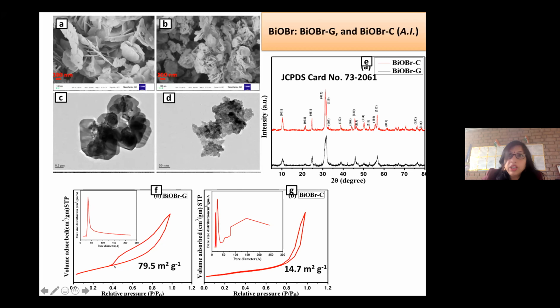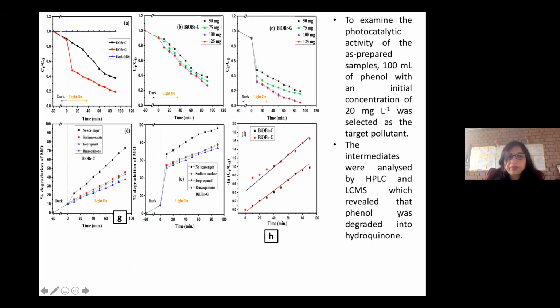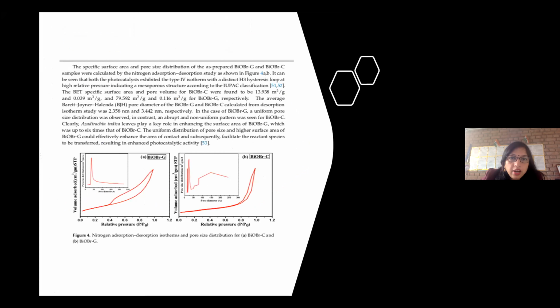And when we saw this BET surface area, by BET we found that the surface area was enhanced approximately 5 to 6 times. And then the activity was checked. Yes, in the green one, the activity was more. You can see this is the chemical one. The optimized limit was 100 mg, and the activity was more in the case of the green one. And then the scavengers showed that all species are responsible in both. And then the kinetic model, and then the surface area was enhanced.